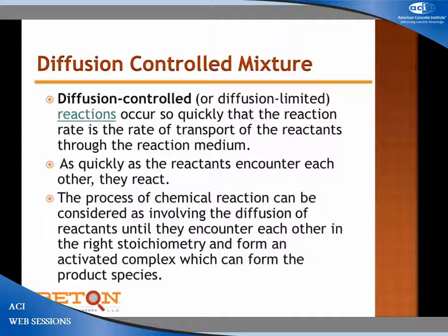One mechanism of doing that is to put finely divided, inert or otherwise, material so that you have more surface upon which the calcium silicate hydrate can deposit. When you do that, you get more strength out of less cement, which David showed you in his slides. See, the best part of being last is everyone's covered all of my points already.